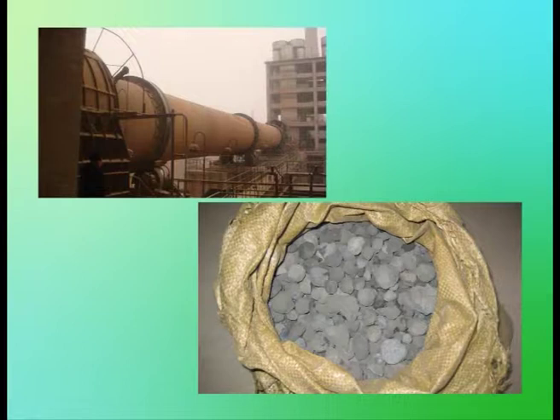Cement making. Cement clinker is manufactured by heating the blended and ground raw material, typically limestone and clay or shale and other materials, to partial fusion. The clinker burn takes place at a temperature of 1450 degrees Celsius in kilns, which are normally inclined, rotating cylinders lined with heat-resistant bricks. Clinker emerges from the kiln after several hours as granulated spherical pebbles.